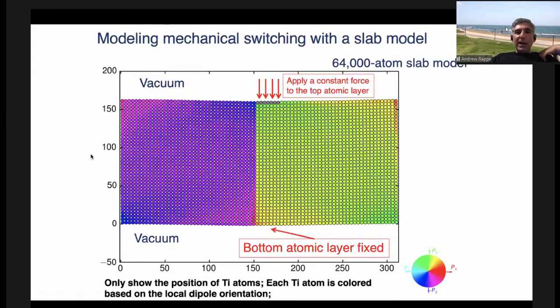Okay, so my group has developed over the years an interatomic potential so we can model ferroelectric materials using all atom simulations. Here we're reporting results from a 64,000 atom slab model of lead titanate. So this is PbTiO3. I would say we've done up to 2 million atom calculations. That's the largest we've gone. So this is well within our capabilities.